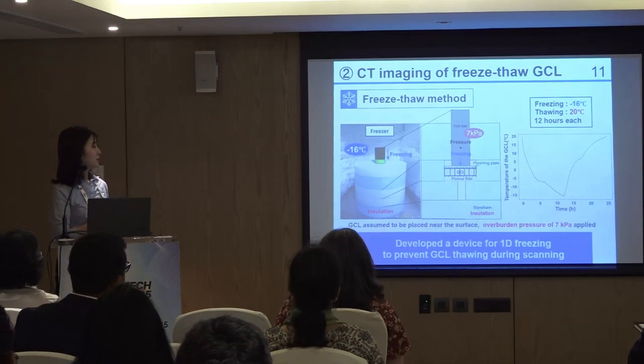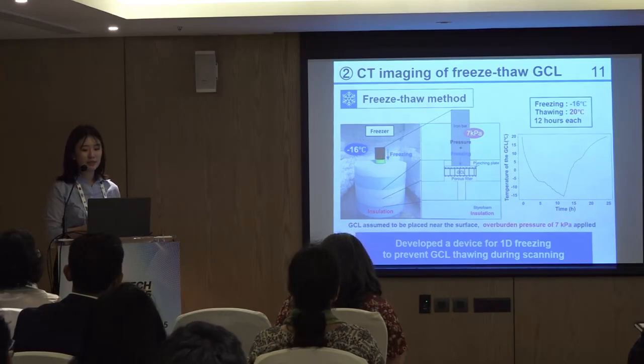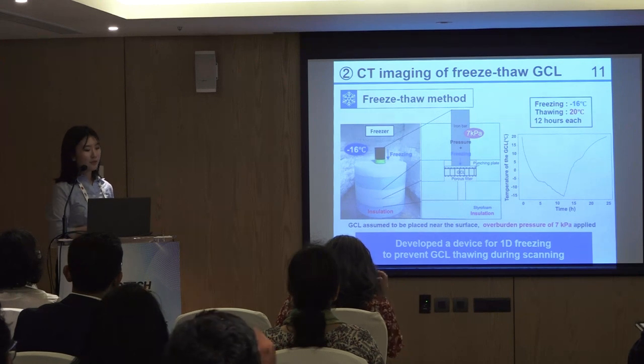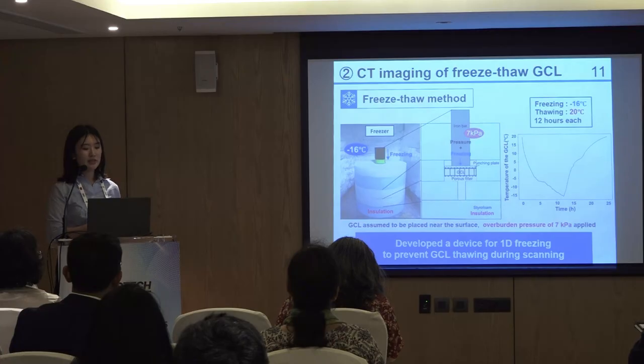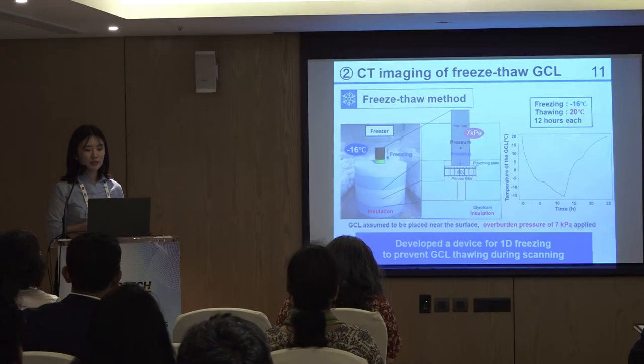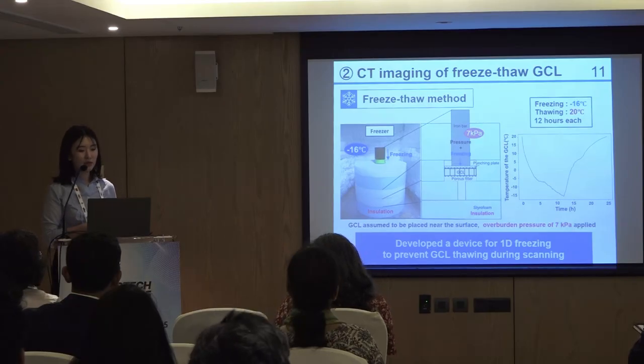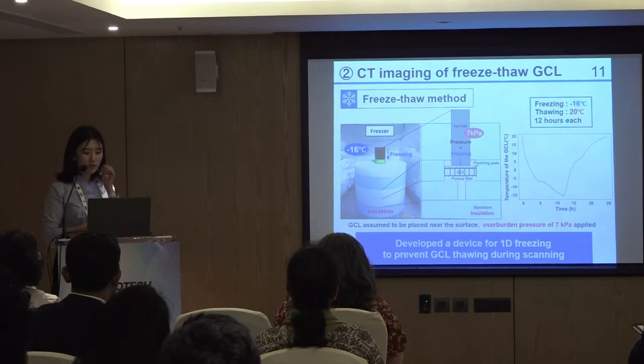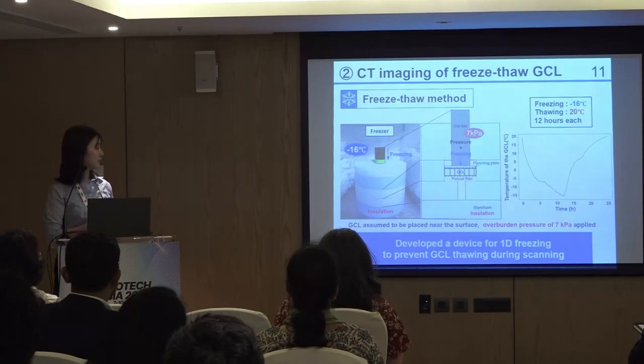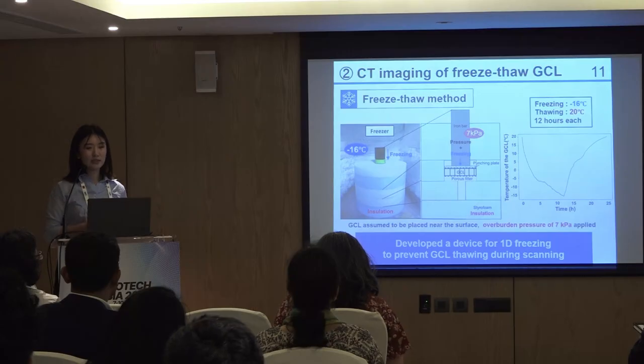Freezing was carried out at minus 16 degrees Celsius, same as in the nano CT observation, and thawing was conducted in a room maintained at 20 degrees Celsius. In our preliminary experiment, we measured the internal temperature of the GCL and found that each freezing and thawing process required about 12 hours. So we ensured at least 12 hours for both freezing and thawing in this case.